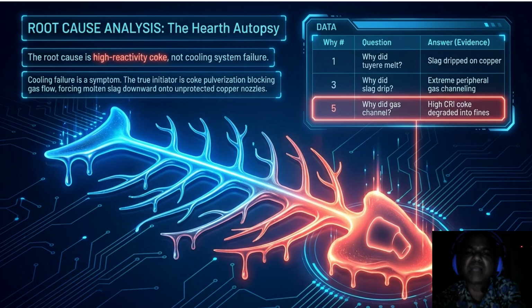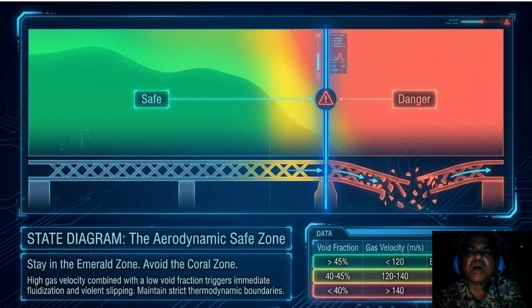So this balance of gas and solid is governed by the law of aerodynamics, which we can map onto a state diagram. So coming to the state diagram, which is about the aerodynamic safe zone. To keep the furnace stable, you must stay in the emerald zone of this aerodynamic state diagram. On the left, we have a breeze representing our burden supported by gas flow. In the emerald zone, where the void fraction is above 45% and gas velocity is under 120 meters per second, you have a smooth descent. But look what happens in the coral zone when the void fraction drops below 40% and the gas velocity exceeds 140: the breeze breaks. This triggers immediate fluidization and violent slipping.